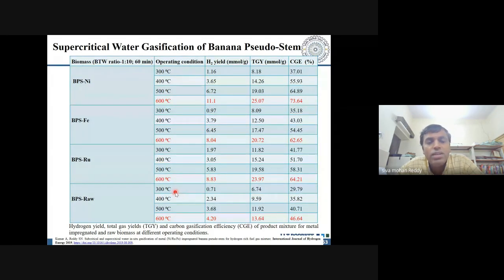So we see that at 300 degrees centigrade, we have a hydrogen yield of 0.71, and we were able to get a maximum of only 4.2 millimole of hydrogen per gram of biomass that has been fed to the system. Okay, and if you look at the total gas yield also, the gas yield is around 6.74 at 300 degrees centigrade, whereas it is raised to 13.64 for raw biomass, and the gasification efficiency is around 30, whereas it is 46.6 at your 600